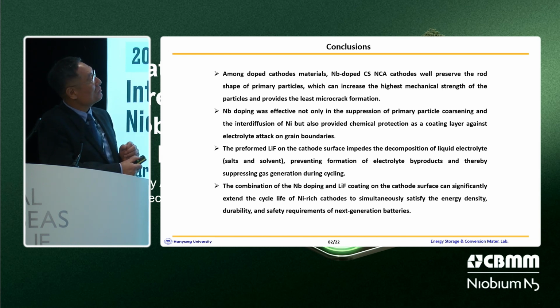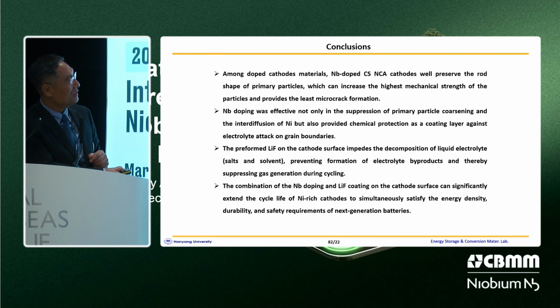This is my conclusion. Among the doped cathode materials, the niobium-doped cathode preserves the rod shape of primary particles, which can increase the mechanical strength and provide the least microcrack formation. Niobium doping was very effective, not only in suppressing primary particle coarsening and inter-diffusion of transition metals, especially nickel, but also in providing chemical protection as a coating layer from HF attack at the grain boundary. The preformed LiF impedes the decomposition of liquid electrolyte, preventing formation of electrolyte byproducts and thus suppressing gas generation. And the combination of niobium doping and LiF coating can significantly extend the cycle life of a nickel-rich cathode to satisfy energy density, durability, and safety for next-generation lithium-ion batteries.